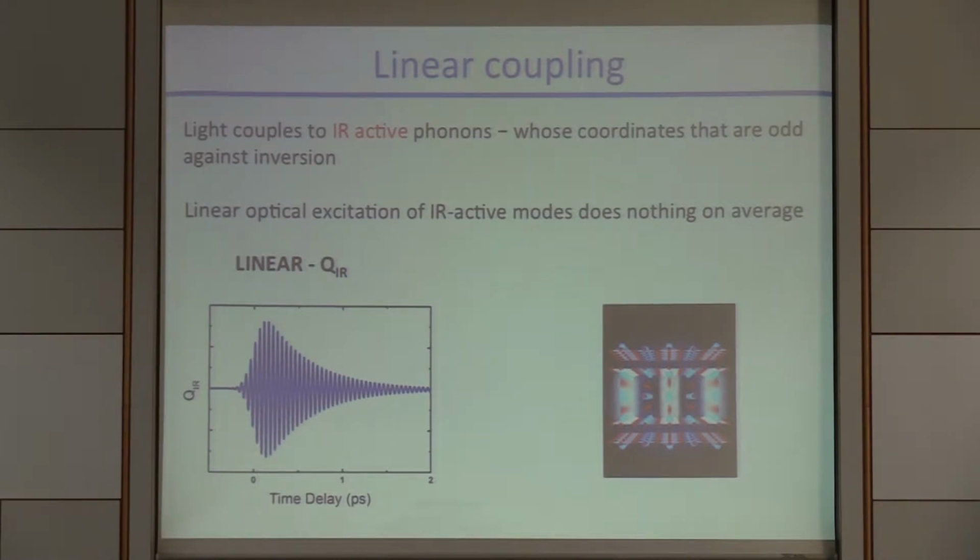This is because the field comes in, has zero vector potential, comes out, and in principle leaves the lattice undisplaced. So if I want to take my yttrium titanate and make it strontium vanadate, or vice versa, I cannot do it simply, as we were thinking at the beginning, by exciting that particular mode. So one needs to do some more thinking. Of course, we are familiar with situations in which one can drive a lattice, for example thermally, and find it in a displaced position, for example by thermal expansion. So there are anharmonic phenomena that average out all the fluctuations and give me a finite average displacement.